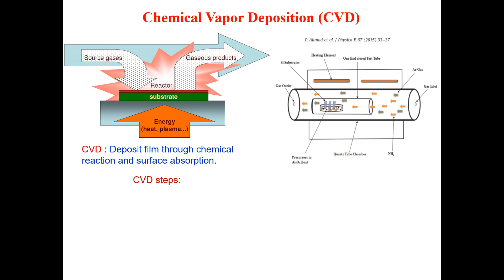The most common steps in the CVD process are as follows. First, reactive gases are introduced to the chamber. Initially, an inert gas such as argon can be flowed to create a rough vacuum and minimize unwanted reactions. If you are not using argon, you can just create a rough vacuum using a rotary pump. The goal is to establish an inert atmosphere before introducing reactive gases.